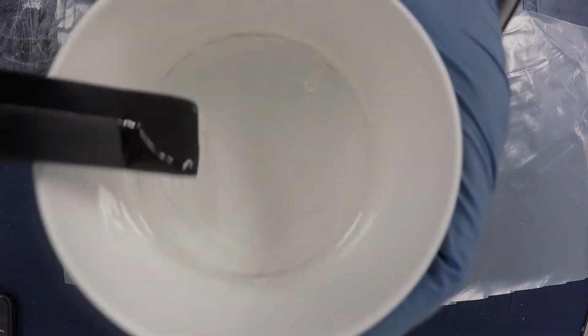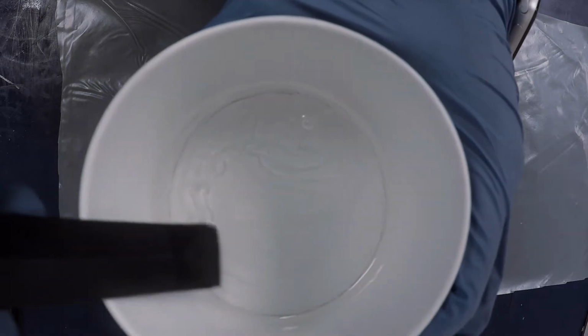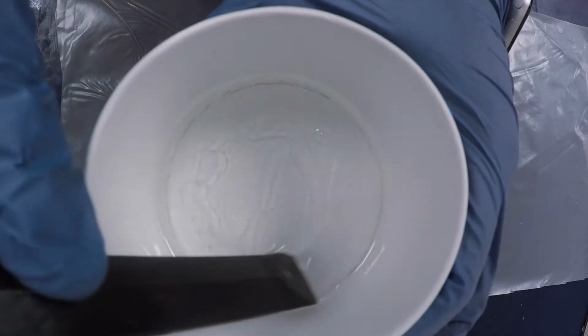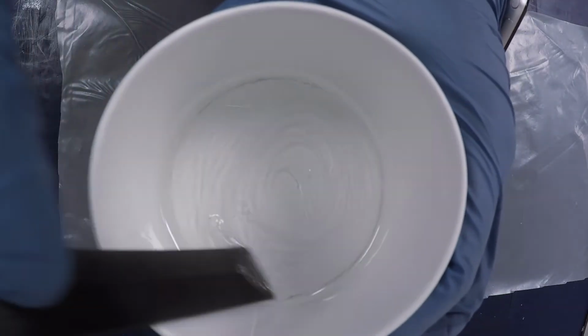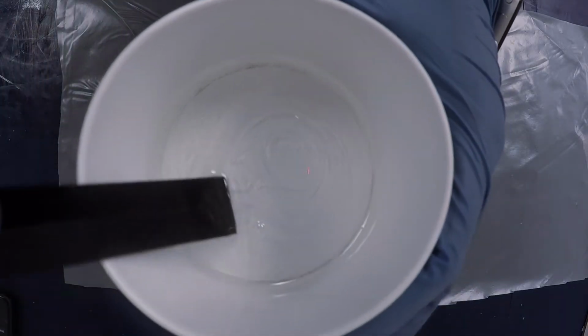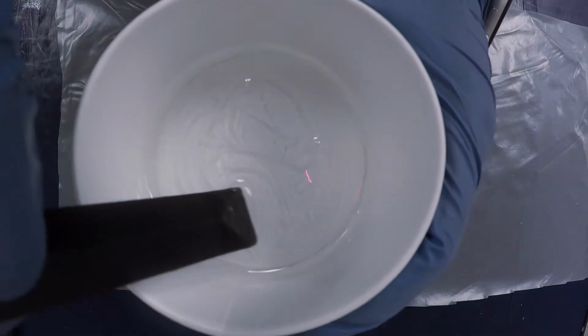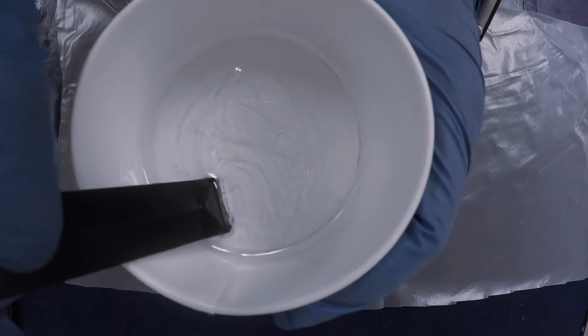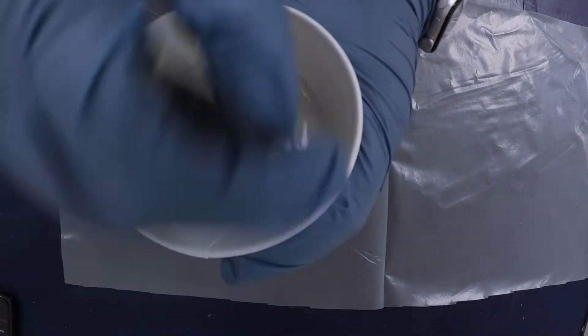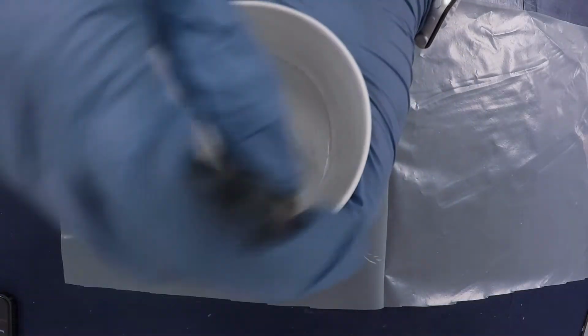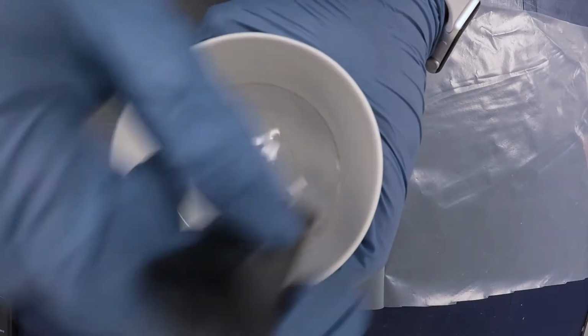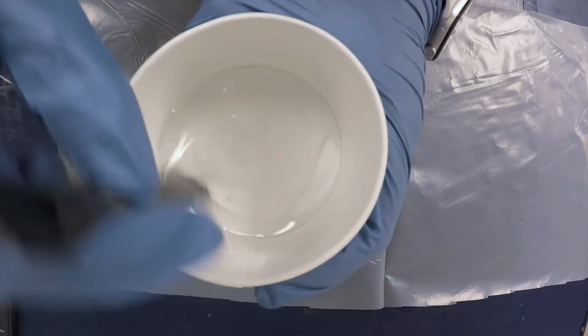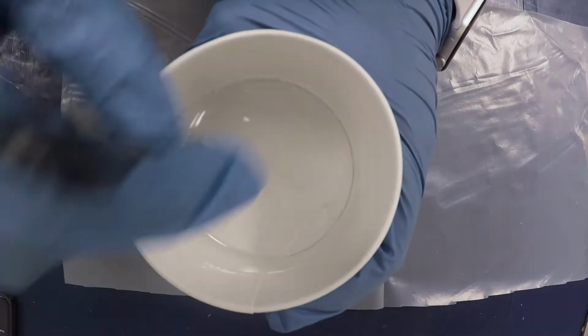As you stir the epoxy, you will notice that the unmixed epoxy can be seen by the streaking pattern created by the hardener. When all of the streaking has disappeared, you can determine that your epoxy is fully mixed. Be gentle with your mixing speed and motion to avoid trapping or creating many air bubbles within your mixture. Trapped air bubbles will create porosity in your final component and will negatively affect its finish and performance.